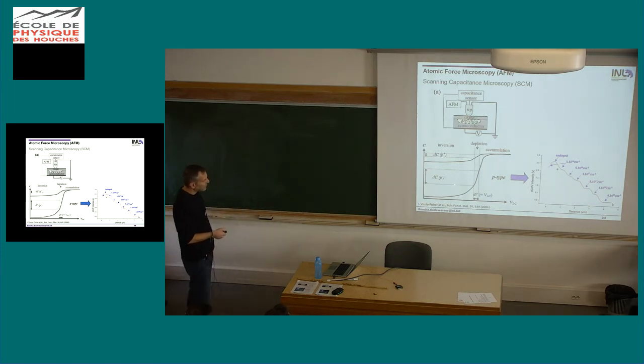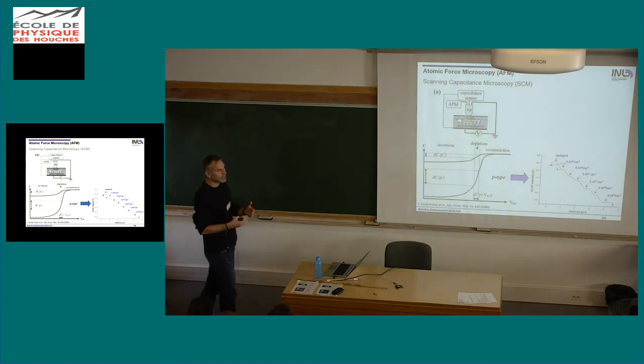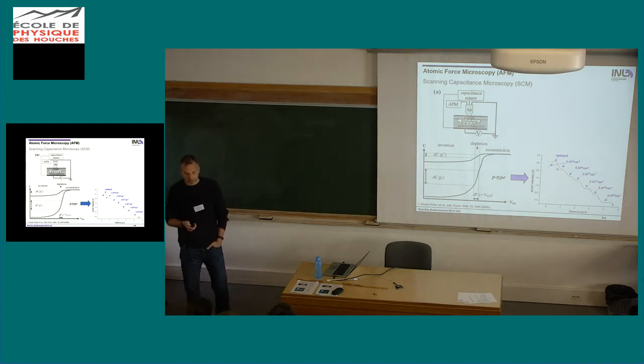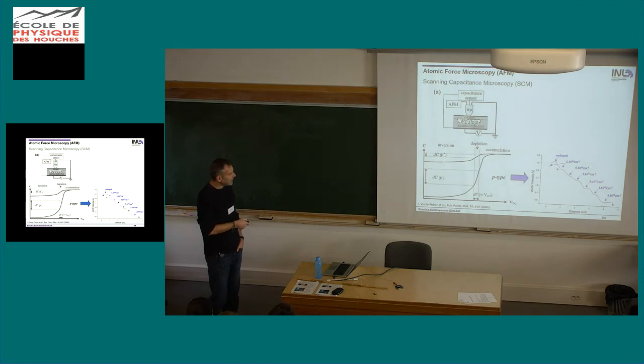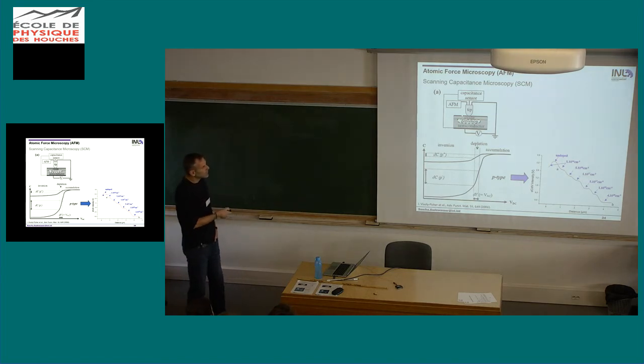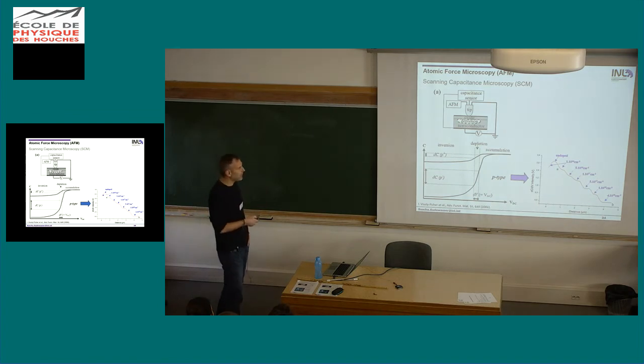So for a semiconductor that is lowly doped, that capacitance change as a function of voltage is very large. The reason is there are not a lot of charge carriers available, so my depletion region gets quite large, and therefore I get a large capacitance. On the other hand, if I have a highly doped material, here in this case P+, then to screen that same voltage, I have a much narrower depletion region, and therefore my capacitance change is much smaller.